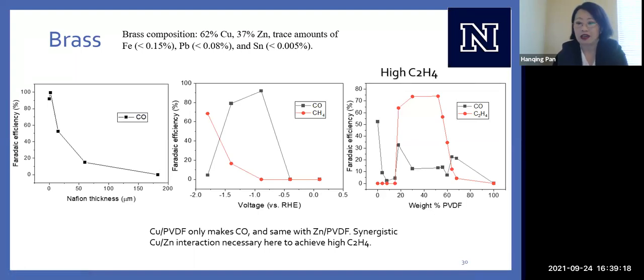This is interesting because copper PVDF does not do this. Zinc PVDF does not do this. But copper and zinc together as brass with PVDF makes high amounts of ethylene. So again, there's some kind of special interactions going on between the copper and zinc that's necessary here for us to achieve this high ethylene yield.